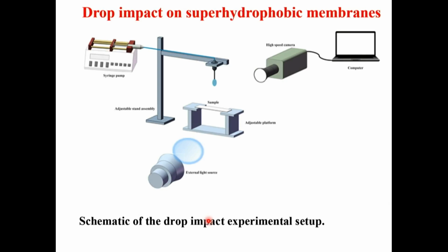So now let's come to the applications essentially. Okay, so electrospinning is essentially a tool to make some protective layers in my mind in this work, and we wanted to test how this superhydrophobic nanofiber membrane protects from penetration of water through it. And water essentially comes in many cases as just rain, so that's a rainy experiment you can organize. It's a very simple one. You drip droplets from different heights, so that regulates the velocity of impact, and you can easily start from 1 meter per second and reach 5 meters per second, and this covers the entire range of droplets in rain. So that's exactly the range of interest.